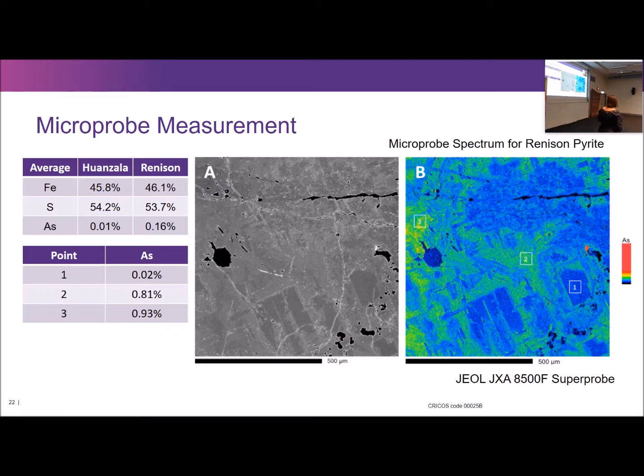Again, an interesting textural observation. If you look at just the large-scale scanning electron microscope image, you see these 90-degree angles cropping up again, and areas of smooth texture contrasted with areas of rough, slightly pitted texture. And these correspond almost exactly to regions of high and low arsenic, but not a single grain boundary in sight.